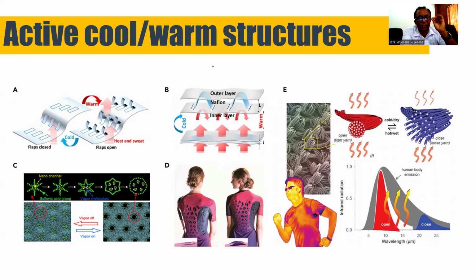So just to summarize, the thermal transmission rate will significantly reduce if there's a cellular structure, cavity or pore structure in the material, and the geometry, distribution, and size of the pores have a very special effect. Especially at small pores, the transmission rate can be exponentially reduced in certain cases. If you take aerogels, the lowest thermal conductivities known to man are produced by introducing pores to these structures.